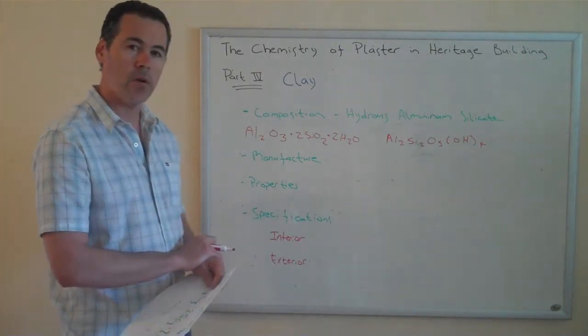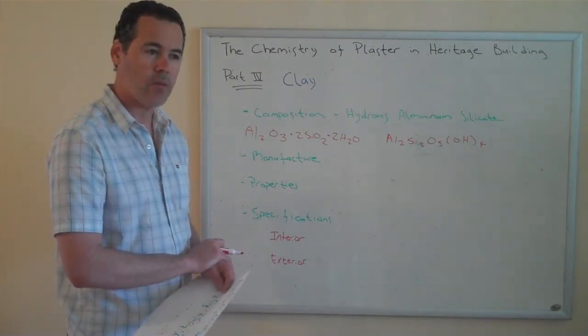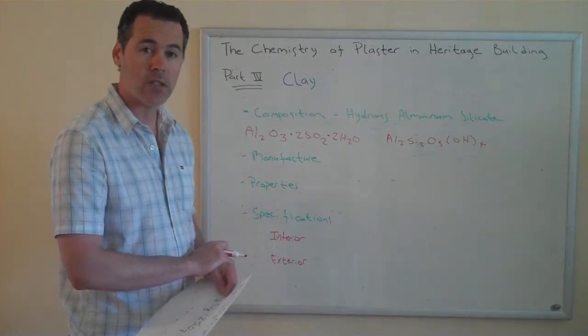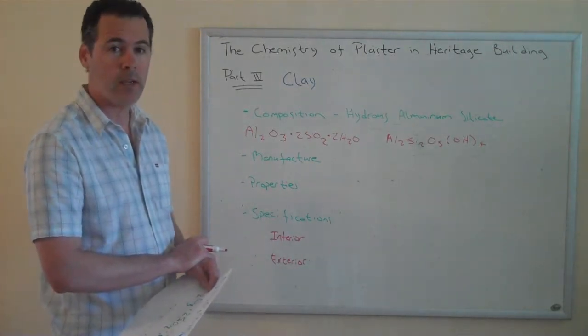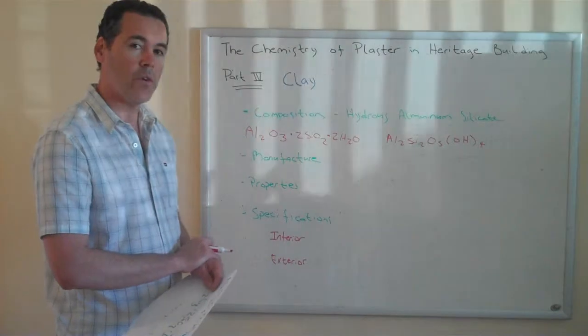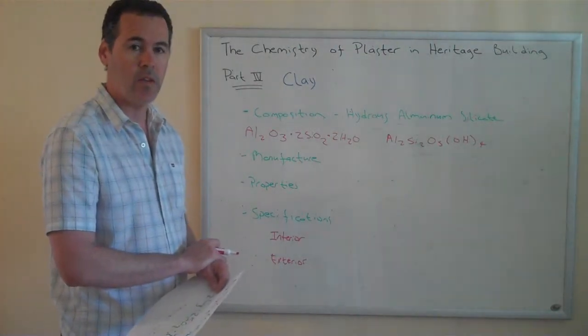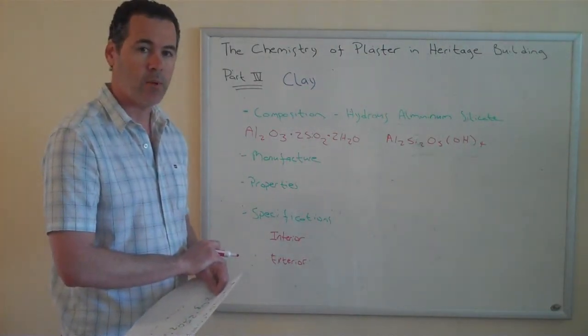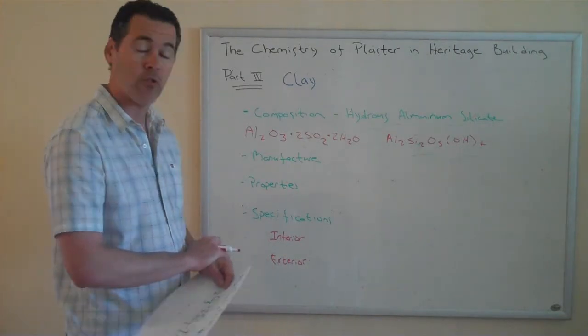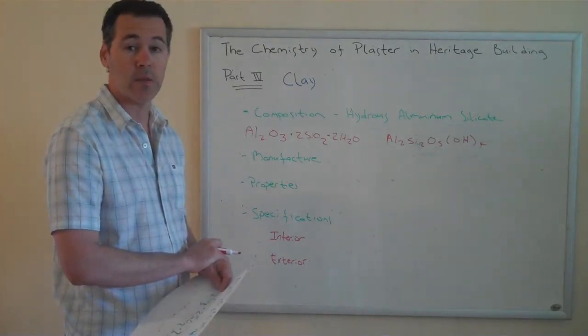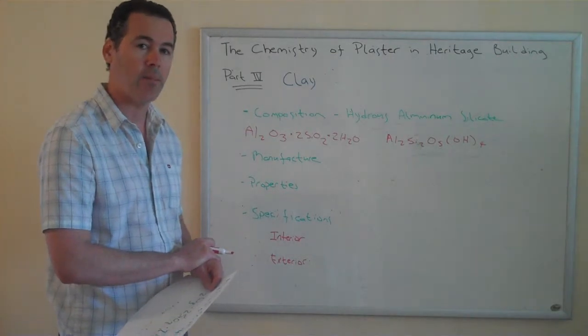However, if you're in a climate that is subject to freeze-thaw cycles or a lot of rain, clay can also be used, but it needs to be stabilized. That can be done with a mixture of natural hydraulic limes which are very effective, and sometimes natural cements, depending on the climate.